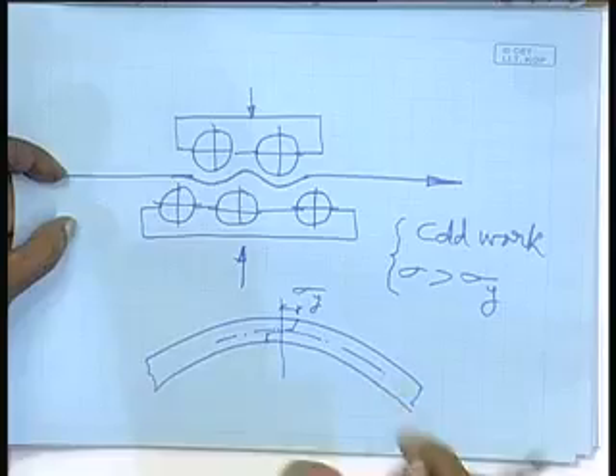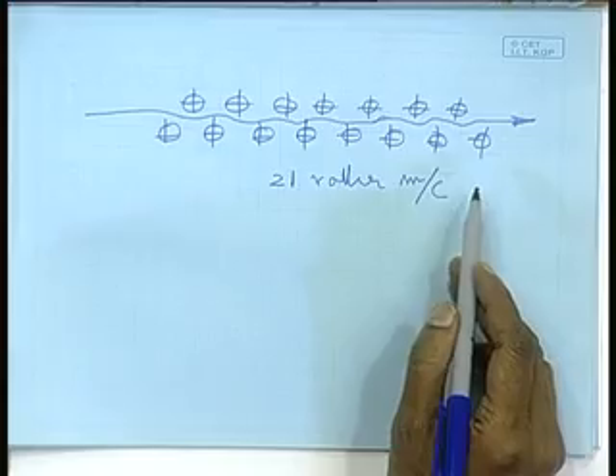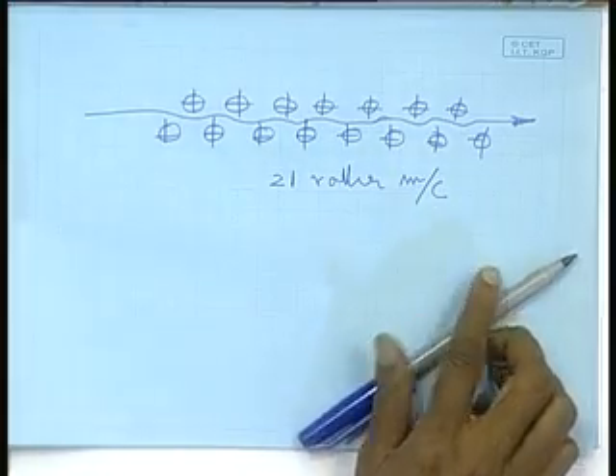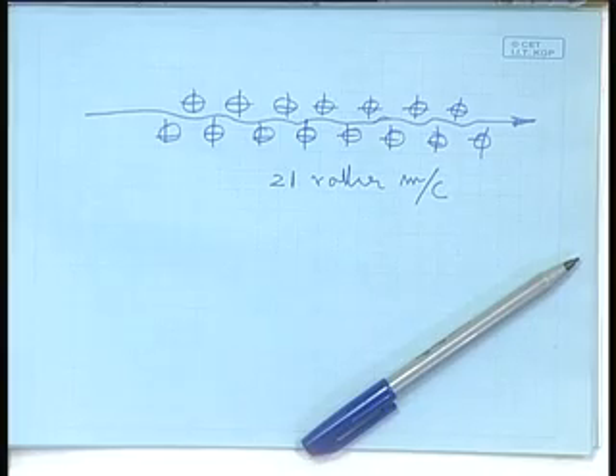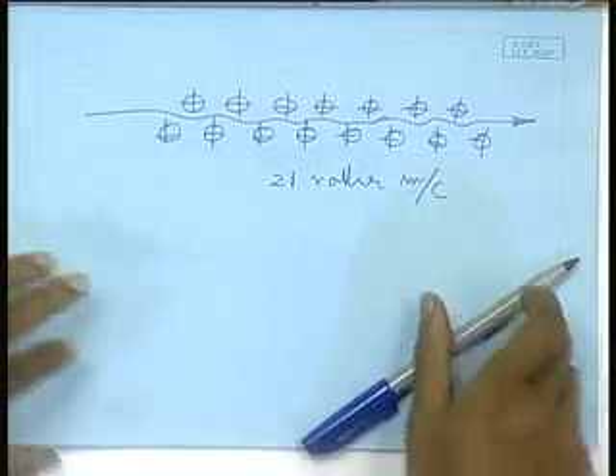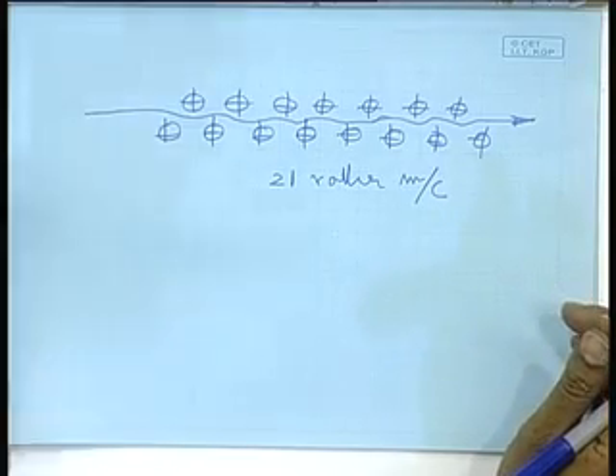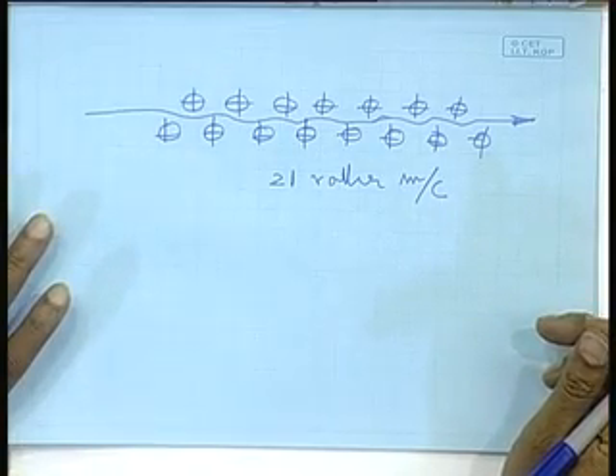That means, if I have, say, a 6 millimeter plate to be straightened and stress relieved, you may need to do this operation of bending it in this direction, and again in the opposite direction, several times more compared to a plate of, say, 20 millimeter thickness. A thicker plate requires a straightening machine with fewer rollers, thinner plates require more rollers. So, generally, up to 10 millimeter thick plates, a 21 roller machine is required, whereas for, say, 16 millimeter and above, a 5 roller machine will do.